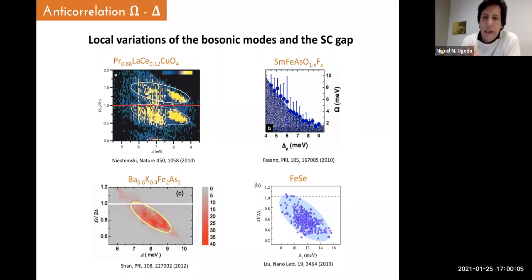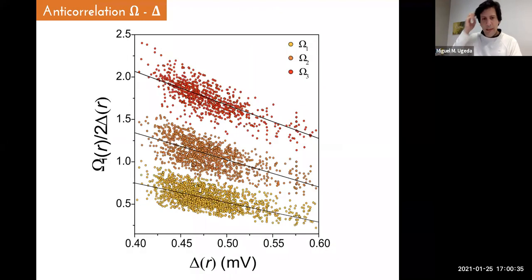show this anticorrelation with oscillation or fluctuations of the superconducting order parameter in space. So oscillations due to, for example, the presence of defects or charge puddles, etc., intrinsically present in the superconductor. So we had to do the same in order to make sure that this anticorrelation is real and it's not just followed in the magnetic field. And so this is what we did. And here is the plot for the first three modes that we observe.